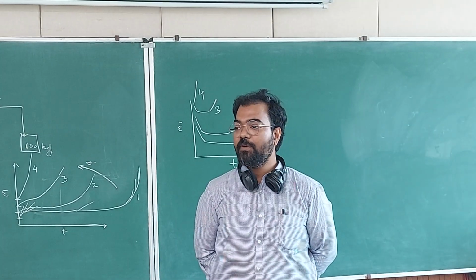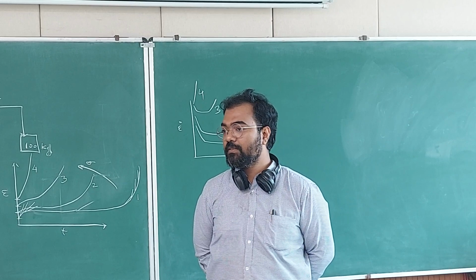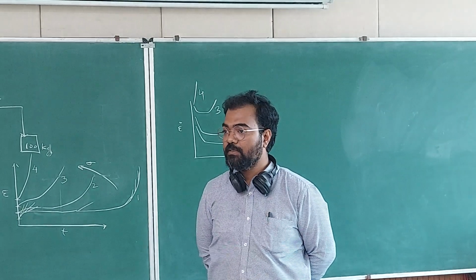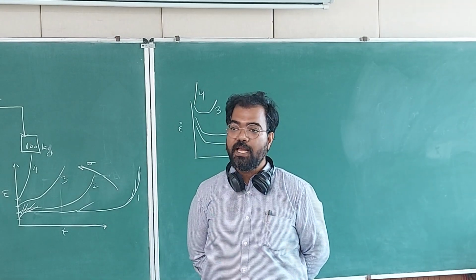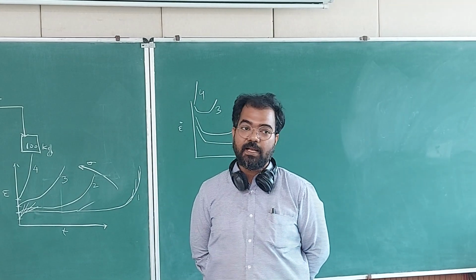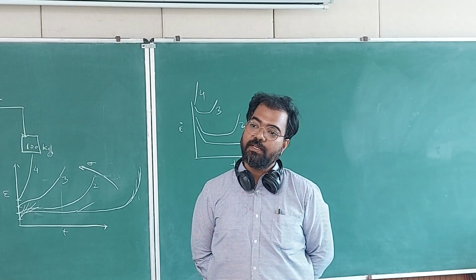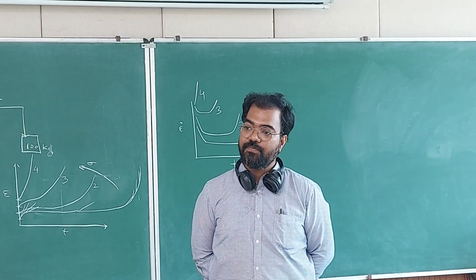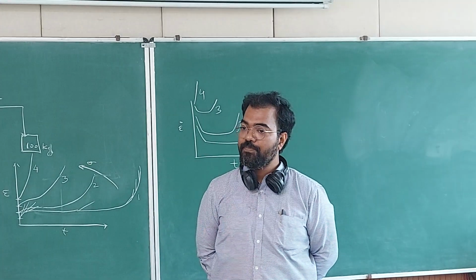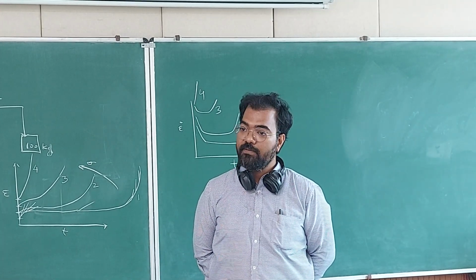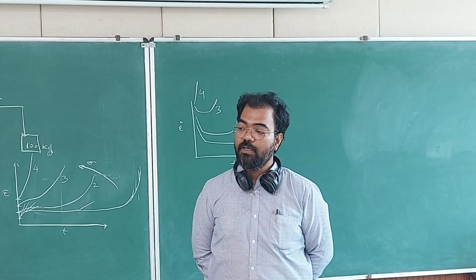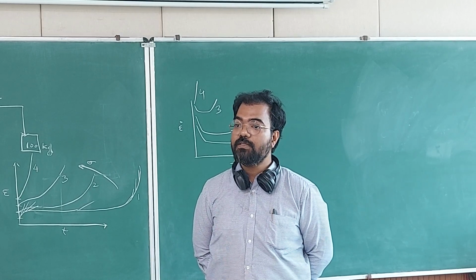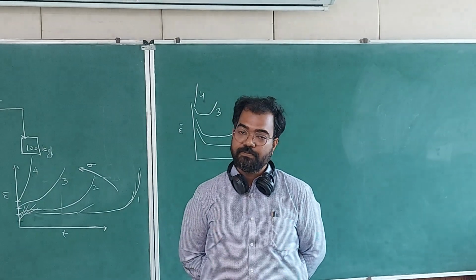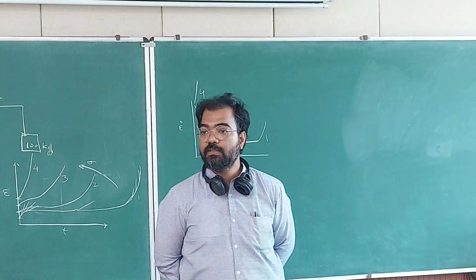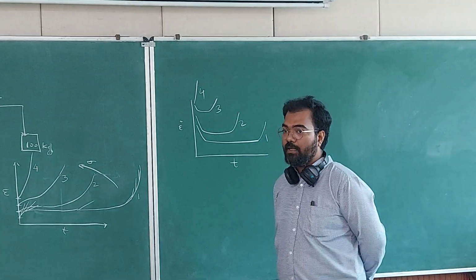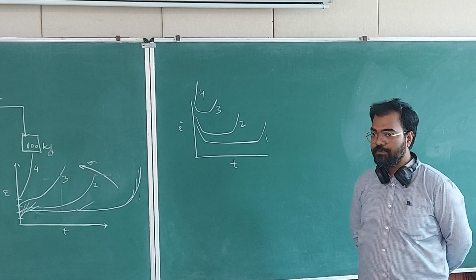There is no reason why climb cannot happen, except time is less. But that doesn't mean climb is not happening. Climb is happening. Strain hardening is also happening. Climb is also happening. If the temperatures are very high, then grain boundary sliding will also be happening. And then stress induced diffusion will also be happening from grain boundary and within the grains. All those things are happening. It is a net result which you are seeing.